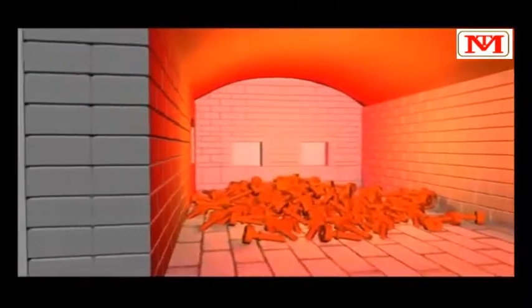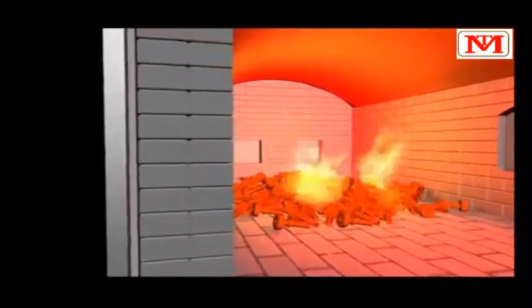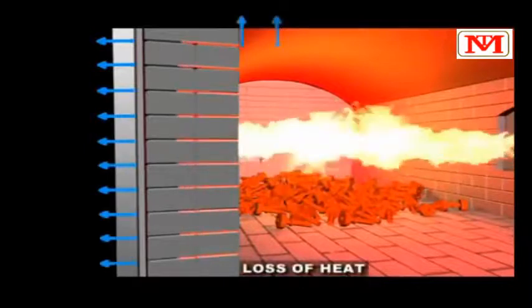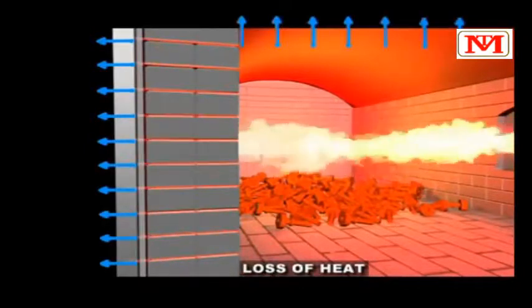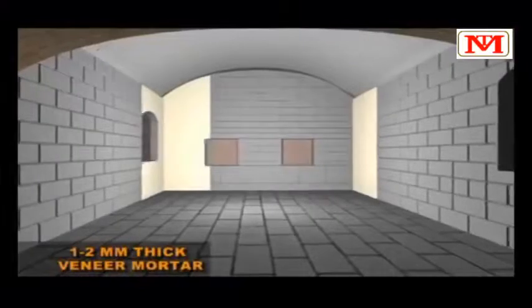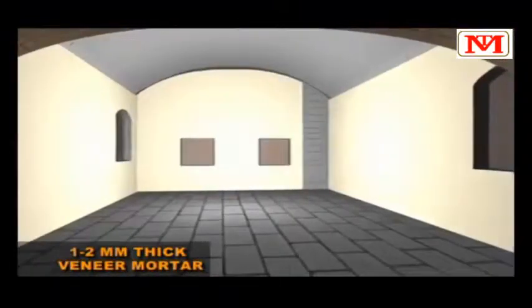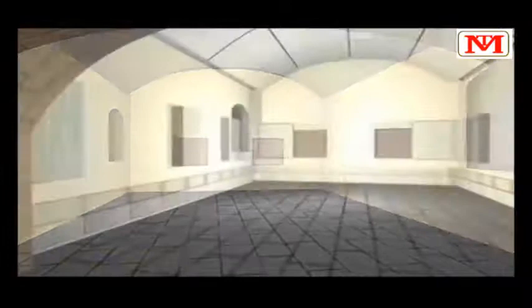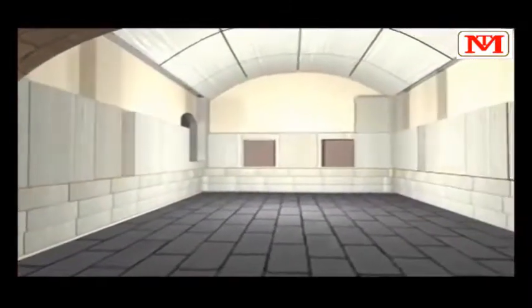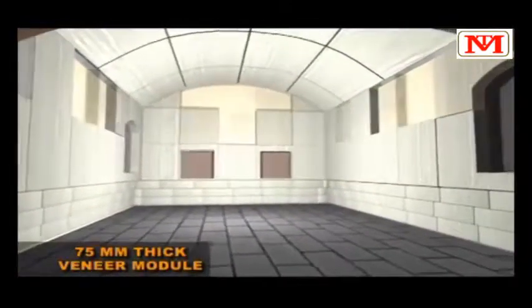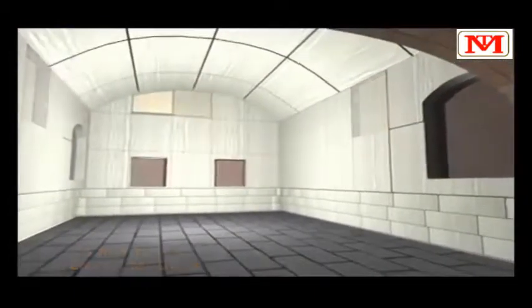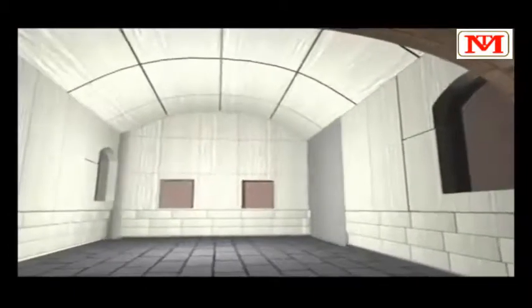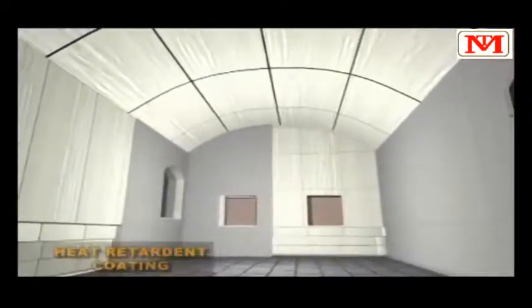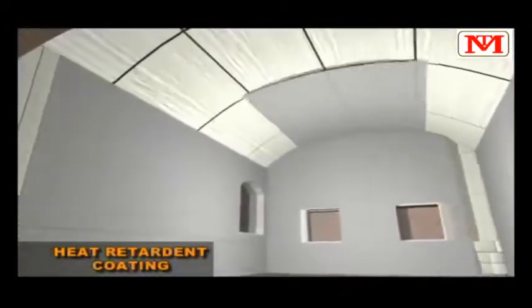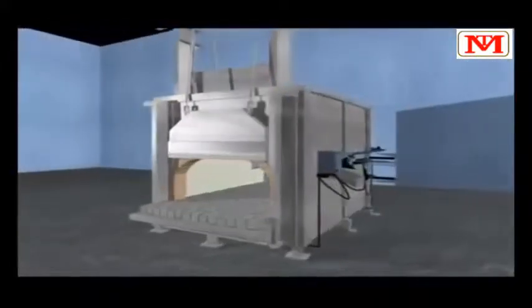In this process, considerable amount of heat is lost due to the amount of heat absorbed by refractory material and radiation losses. To reduce these heat losses, the project team proposed veneering process. In this process, 75 mm thick veneer modules made up of ceramic fiber were pasted on the hot face refractory lining with the help of veneer mortar. Once the veneer modules were set, a heat resistance coating was applied on the veneer module to increase surface emissivity.